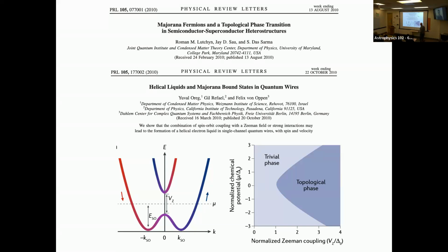And that's what happened more or less at the same time in these couple of papers, and they studied the problem of a certain spin-orbit coupling, a certain applied magnetic field, and a certain superconducting gap, and found that in fact a topological phase of superconductivity exists. It exists in a place where, normally, if you have a tiny bit of background in superconductivity, you'd think the condition for destroying superconductivity is met.